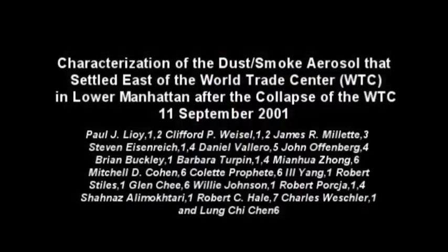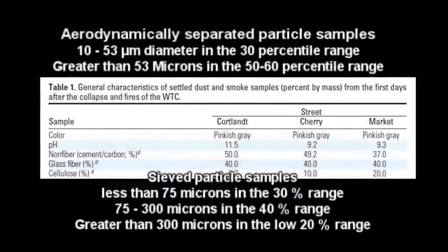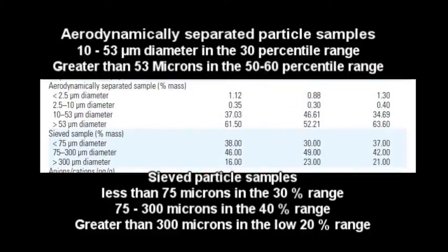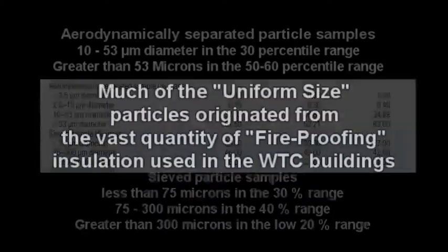Characterization of the dust, smoke aerosol that settled east of the World Trade Center. Aerodynamically separated particle samples: 10 to 53 micron diameter in the 30 percentile range, greater than 53 microns in the 50-60 percentile range. Sieved particle samples: less than 75 microns in the 30% range, 75 - 300 microns in the 40% range, greater than 300 microns in the low 20% range.